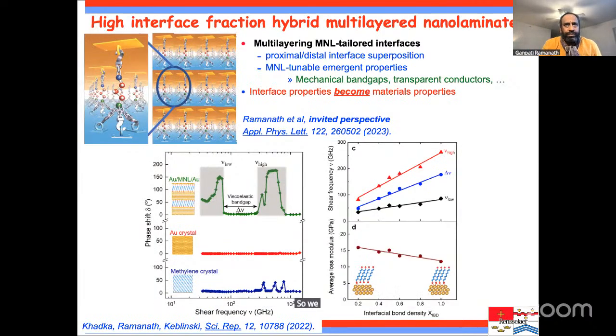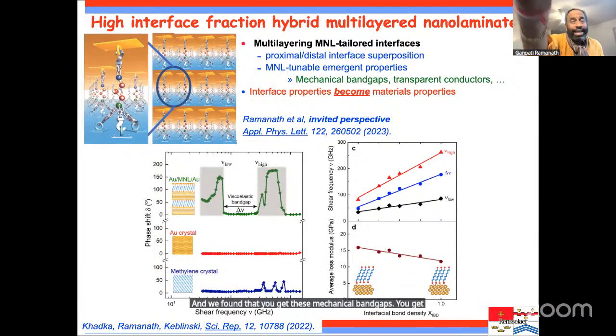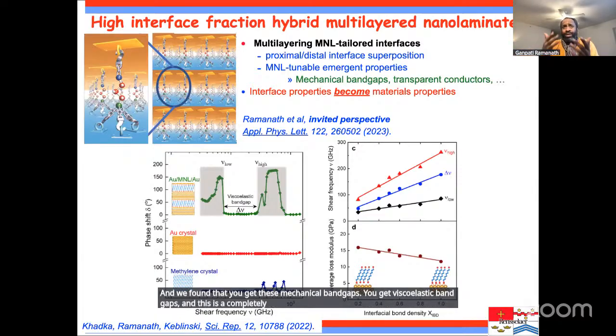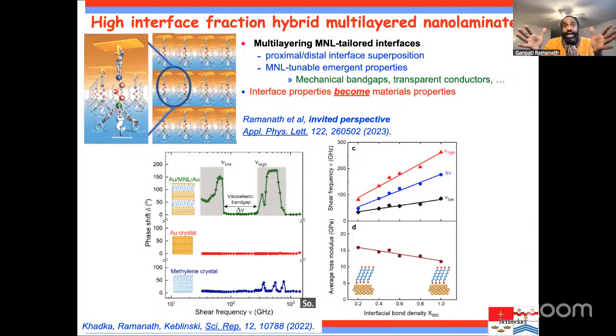So we did some simulations of these with a colleague, Professor Keblinski, who's in my department. And we found that you get these mechanical band gaps. You get viscoelastic band gaps, and this is a completely new concept. You all know electronic band gaps, photonic band gaps, phononic band gaps. So in the mechanical regime also, you can actually find this.